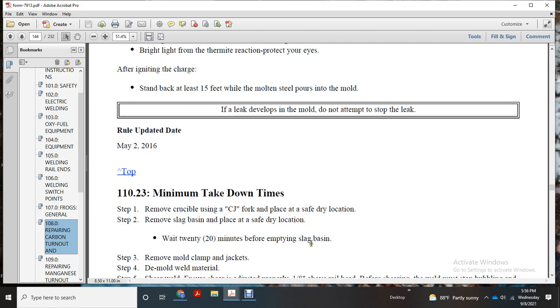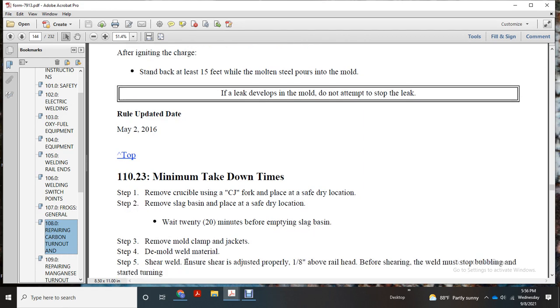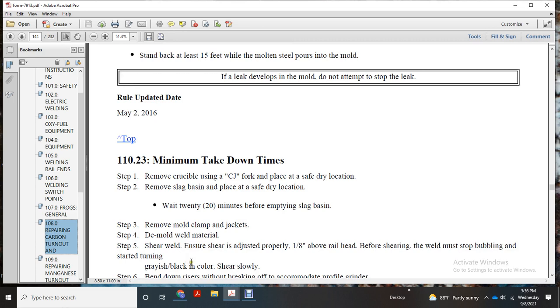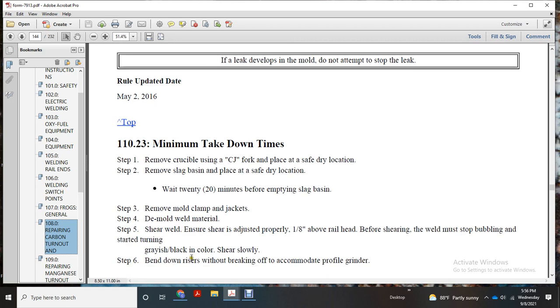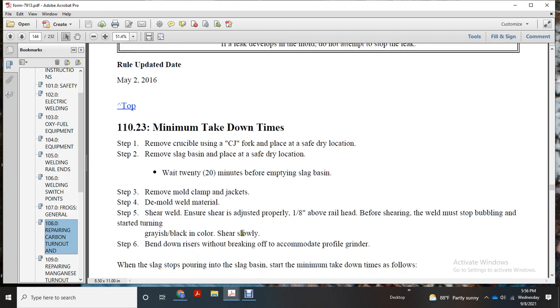Wait 20 minutes before emptying the slag basin. Remove mold clamp and jackets. Demold the weld material. Shear the weld. Ensure the shear is adjusted properly, 1/8 of an inch above the railhead. Before shearing, the weld must have stopped bubbling and started turning a grayish black color. Shear slowly, bending down risers without breaking them off, to accommodate the profile grinder.